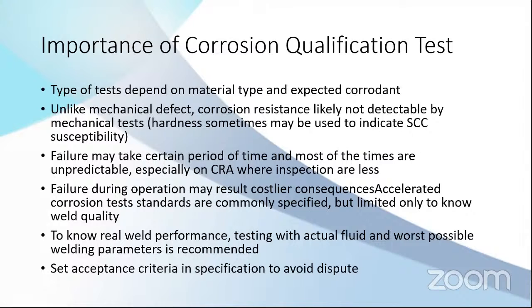This happens a lot because normally in the specification we just say test with ASTM G48. That's it. But now what is the acceptance criteria? And they test, and when the test result is not according to your expectation, then you're going to have a problem, because it's money. You need to test it again, and you spend more money.